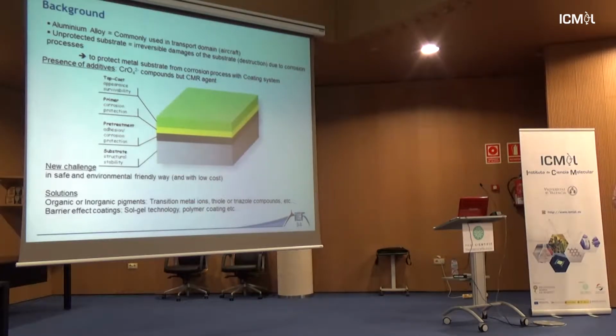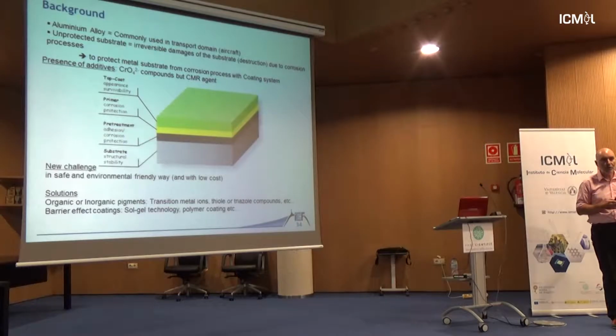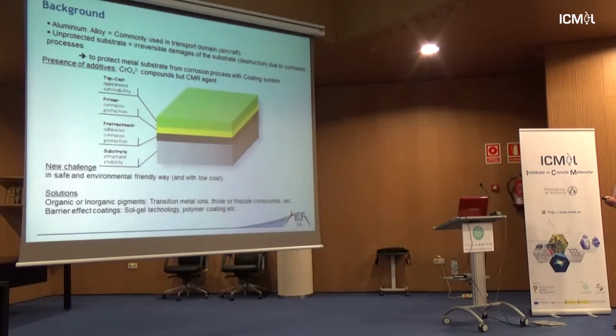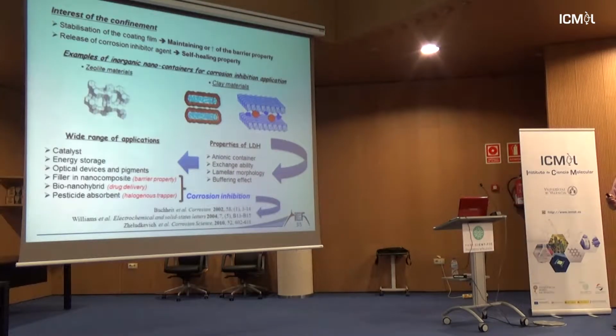So for the primer, the challenge is to change the corrosion inhibition that you previously had in this industry, and they were using chromate, and now it's forbidden for the last 10, 15 years. So you have to find other solutions, and usually it's triazole, benzotriazole, for instance, and cerium oxide, but it's very pricey. So you have to find things to make it more stable. And one appealing aspect is to protect this active additive acting against the corrosion, and to trap them, or to put them in a vessel or container in which they are protected from the polymer chain.